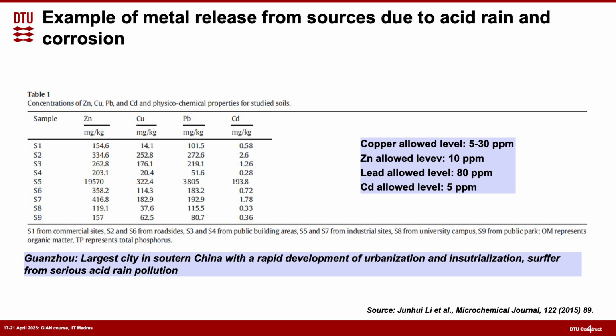If you look here, you can also see that this S1 is coming from the commercial sites, S2 and S6 are coming from the roadside, S3 and S4 are the public building areas, and S5 and S7 are from the industrial sites. Can you see a pattern here? At S5, you can see that the amount of release is much higher in the industrial area, and maybe there is much more pollution there, and that might be the reason for this much higher release of these species around that area compared to the other areas.